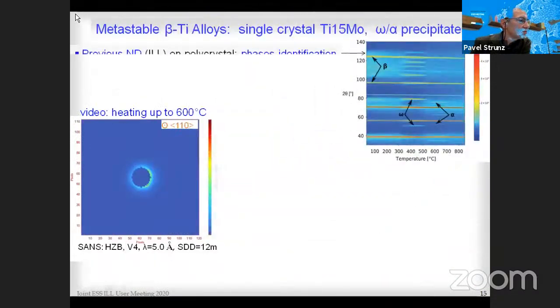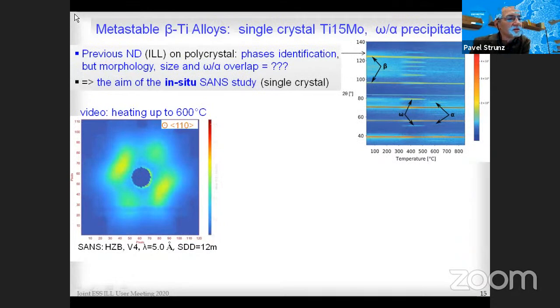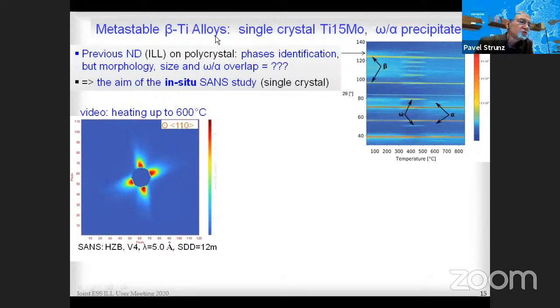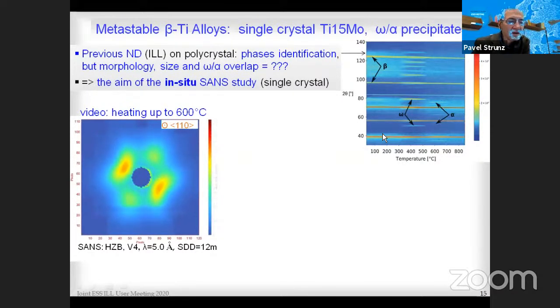But where neutron scattering is particularly strong is in situ measurement. Here it is shown on a single crystal of titanium 15% molybdenum, that means a slightly different alloy than the previous one. The previous neutron diffraction done at ILL was able to identify the phases, but it was not conclusive about the morphology, size, and omega and alpha phase overlap. So that was the aim for the in situ small angle neutron scattering study.